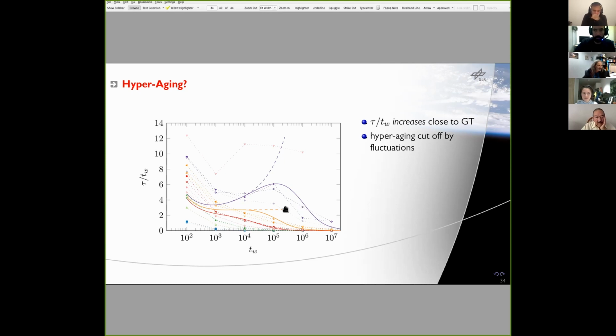This is ideal MCT. And including fluctuations cuts off this constant and eventually causes a decay because the structural relaxation time eventually saturates to a finite value. And interestingly, I think even in the computer simulation data, you see some indications of a non-monotonic behavior. So you see a part where this ratio grows as a function of TW. So this would be a short remnant of hyperaging. And then eventually this is cut off by fluctuations as described by SBR. And that's basically the story I wanted to tell.